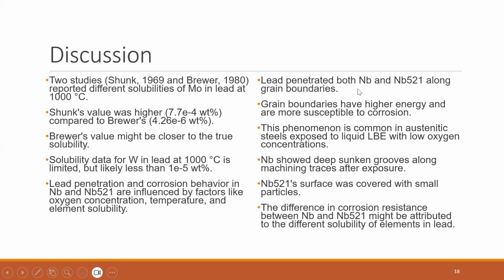Lead penetrates both niobium and niobium alloy along grain boundaries, since grain boundaries have higher energy and are more susceptible to corrosion. This phenomenon is common in austenitic steel, especially in liquid LBE with low oxygen concentration. Niobium showed deep sunken grooves along machining traces after exposure, and the niobium alloy surface was covered with small particles. The difference in corrosion resistance between niobium and niobium alloy might be attributed to the different solubility of elements in lead.